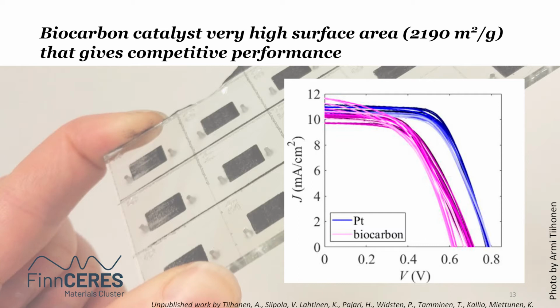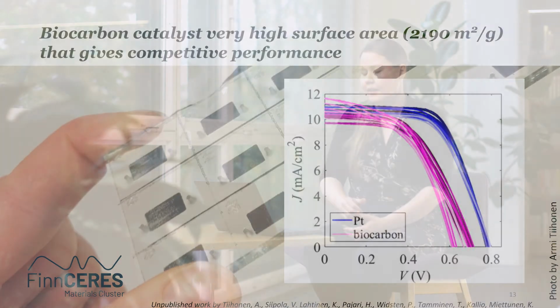So when we look at the results, we could get equally high photocurrent with the biocarbon electrodes compared to the platinum. The only main difference was that the voltage with the biocarbon electrodes was slightly smaller compared to the platinum devices, and we're improving the electrode structure at the moment to reach similar performances.